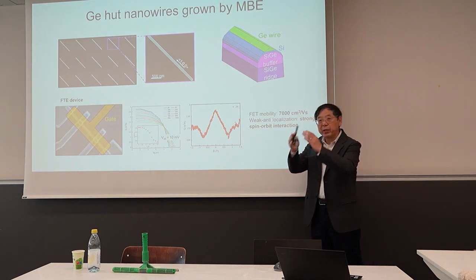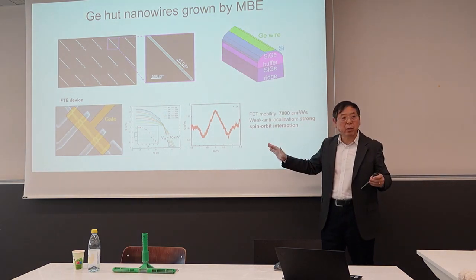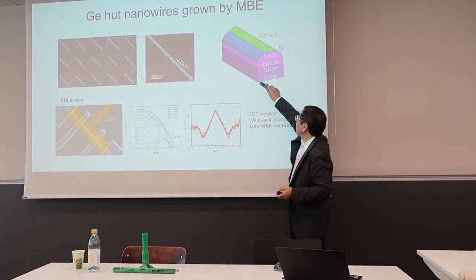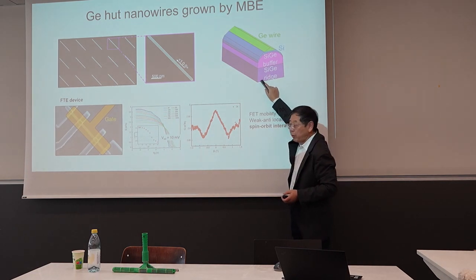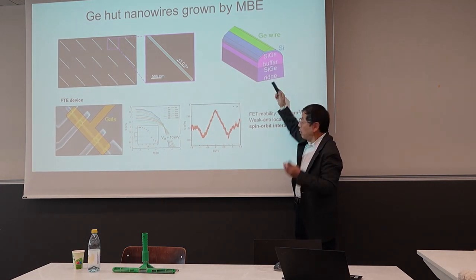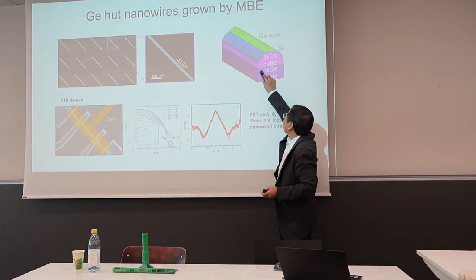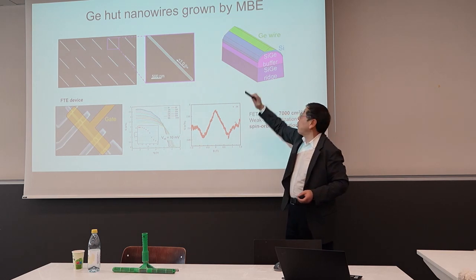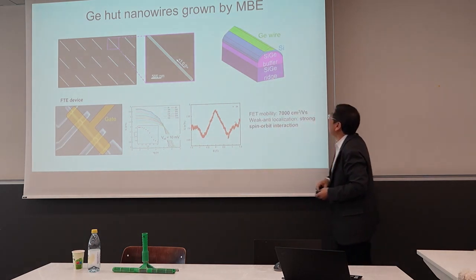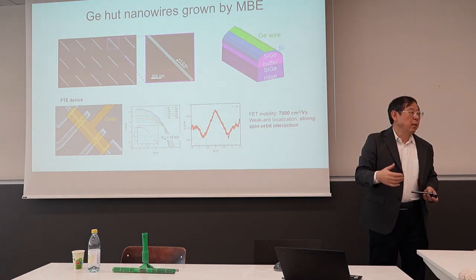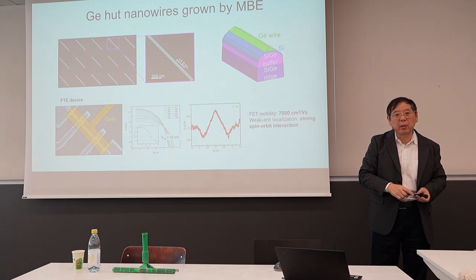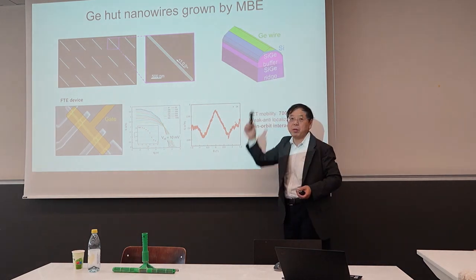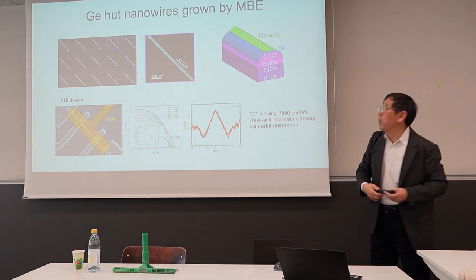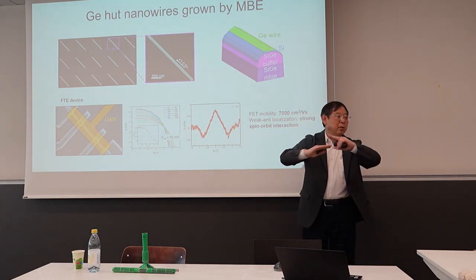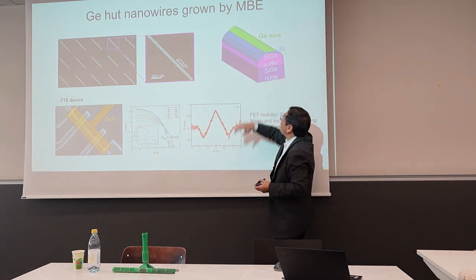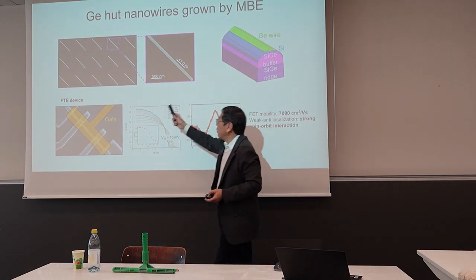Actually, for this nanowire we need an etched ridge. First, we take a silicon wafer. Then we etch the ridge. Then we get the ridge. And then we grow some kind of silicon germanium on top, a silicon germanium buffer. On top of that, we start to grow the germanium wire and cover it by silicon again. And all this is done in situ, which gets a very good interface between the silicon and the germanium wire. And this cross-section shape is a hut type, so we call it hutwire. So this is a hutwire technology, and they grow very nicely.